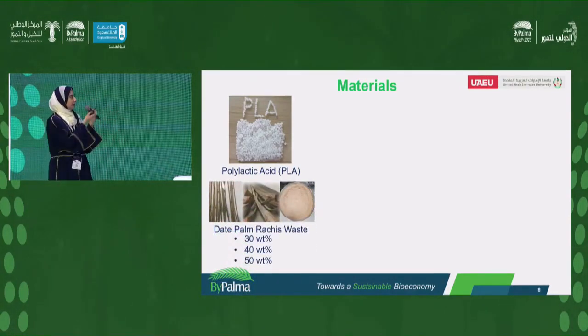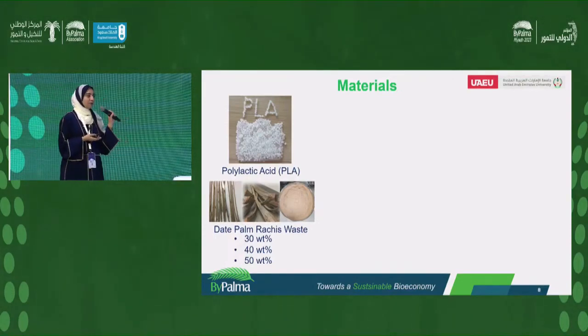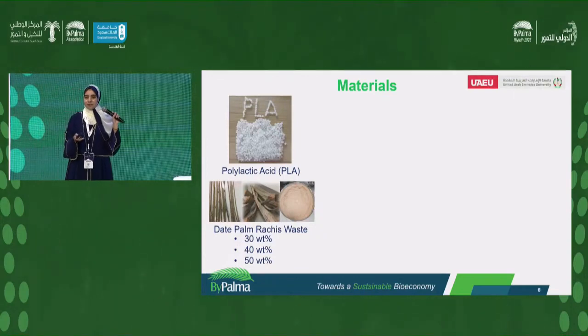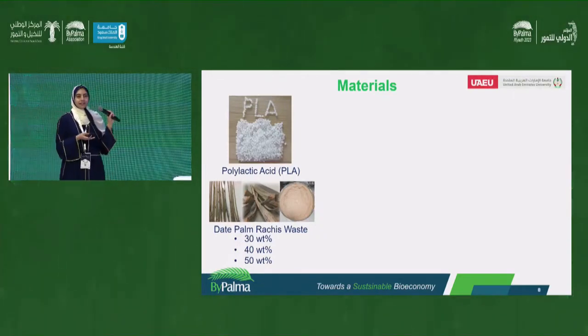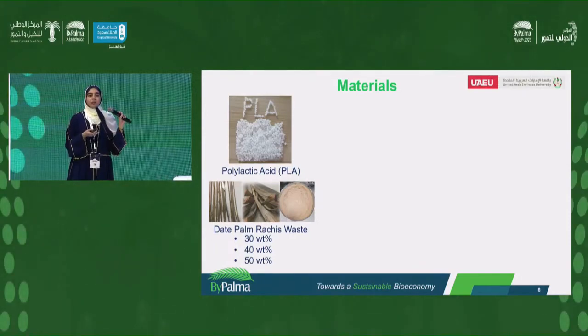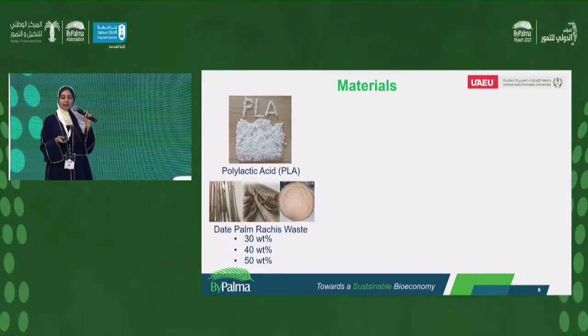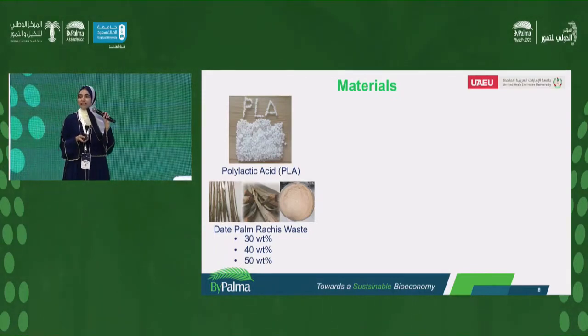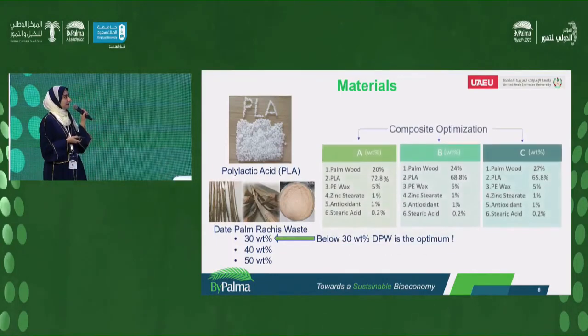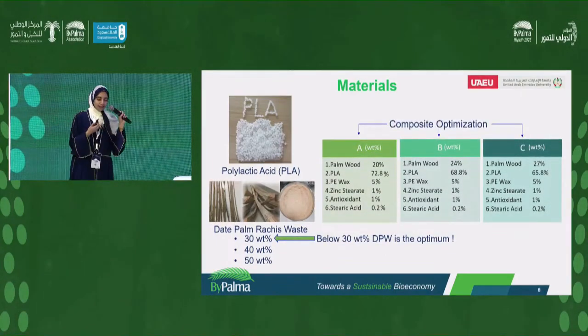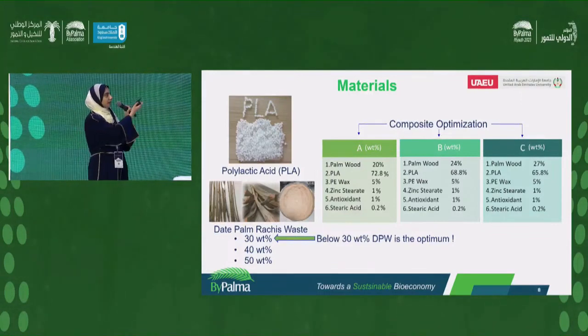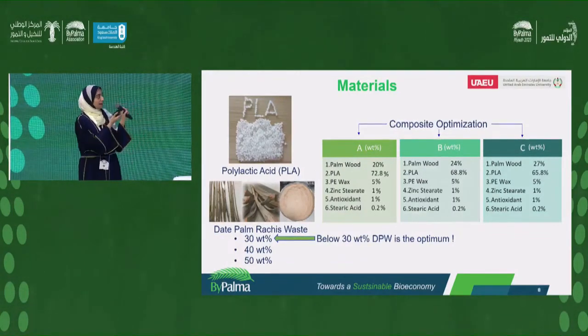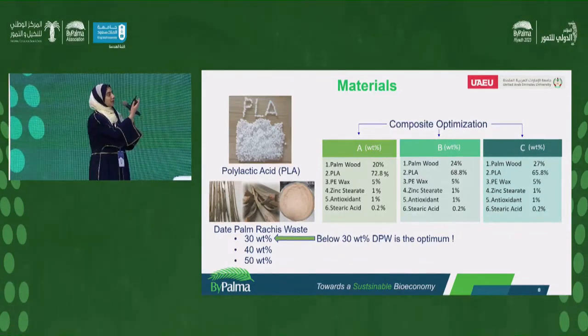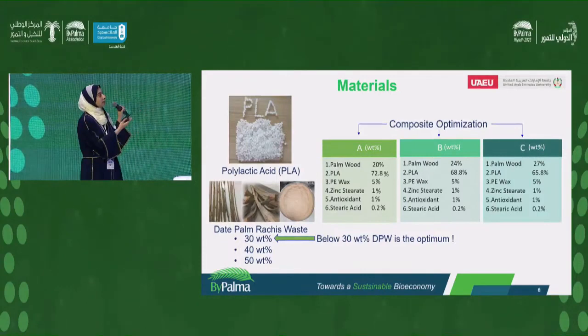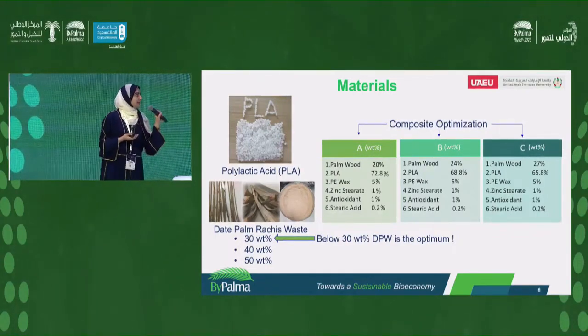Initially, in phase 1, we tested 3 different compositions of date palm waste, which are 30, 40 and 50%. And we found that based on several testing and characterization that we need to go below 30 to ensure the best product performance that can be comparable to the products available in the market. So in this research, I am going to explain some of our characterization related to the 3 optimized formulas, and as we can see, the date palm waste was varied from 20% to 27%, and we used the polyethylene wax, zinc stearate, antioxidant, and stearic acid for this optimization.